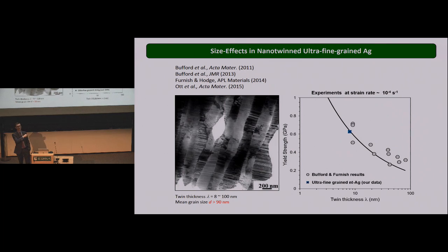So this was about copper. Now let me talk about nanotwin silver. So silver, for the reason I explained, is very attractive because it has a very high electrical conductivity. And so those twin boundaries, in general, do not reduce the electrical conductivity. But by adding twins, we can improve the strength. So we maintain the electrical conductivity, but improve the strength. And so these are just results obtained from different groups, including us here, of nanotwin silver.